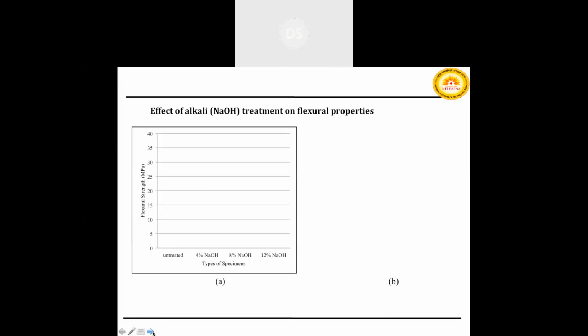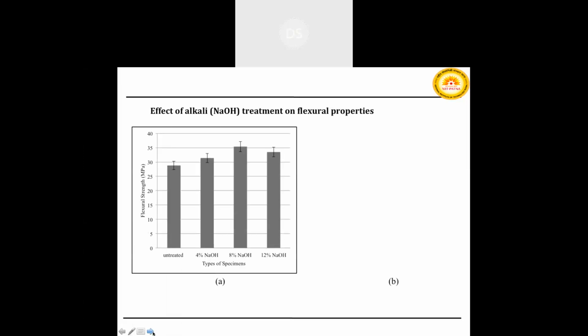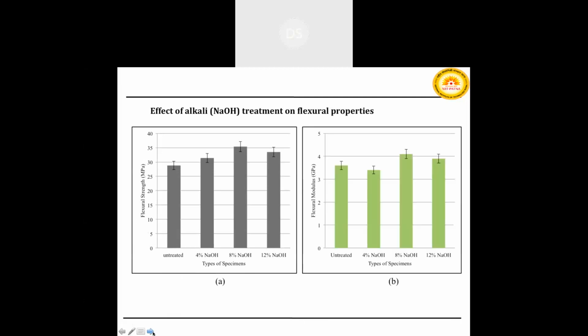The effect of NaOH treatment on the flexural strength of the developed composite. Three-point bending tests were conducted to determine the flexural strength of untreated and treated Borassus fruit fiber. The flexural strength of chemically treated Borassus fruit fiber composites was found to be superior to those made from the untreated fiber. The flexural strength and modulus for the composite with 8% NaOH is maximum in comparison to untreated, 4% or 12% treated. The surface roughness of chemically treated fiber increased due to the removal of unwanted clumps, wax, hemicellulose, etc.